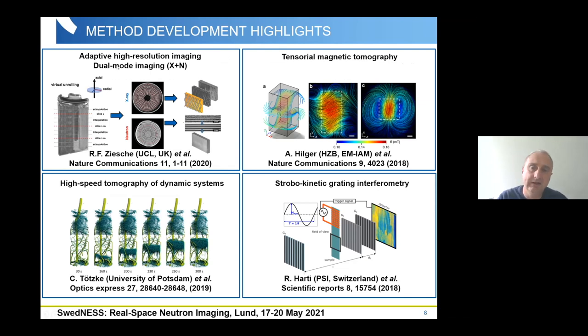So you see here that we went to high resolution, to high speed, in order to push the limits. We developed new methods using contrast related to magnetic interaction, and we were able to reconstruct the magnetic field as a vector. And with new methods where the phase nature of the neutron was approached, we were able to use even interferometry.